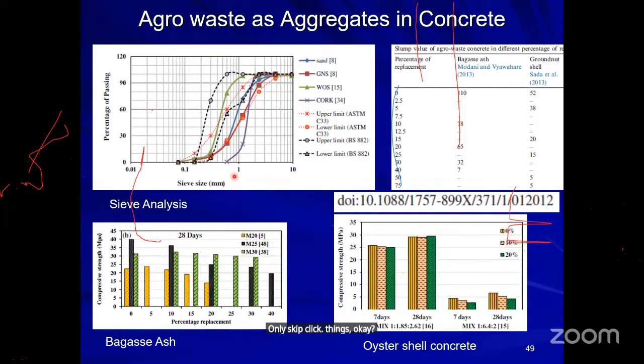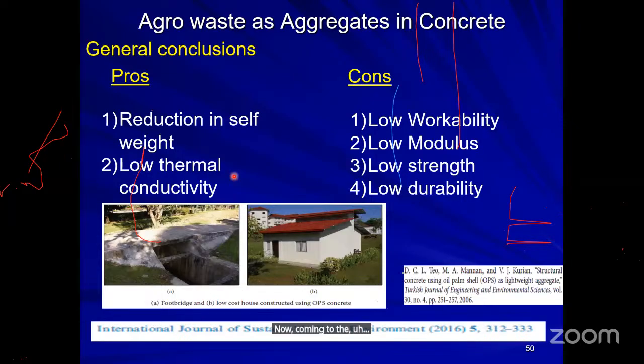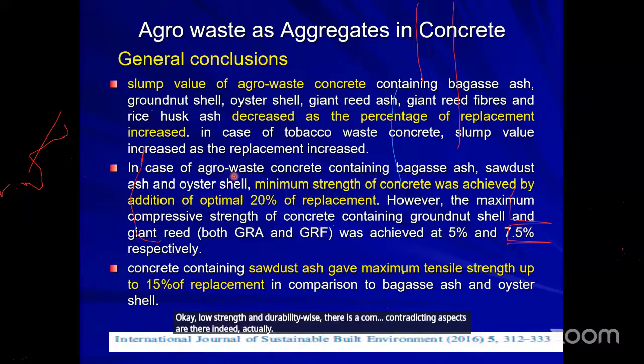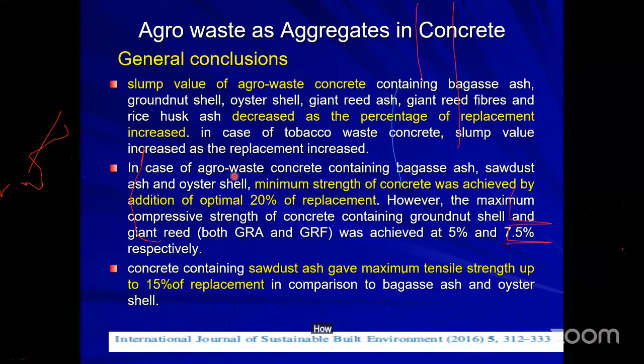Now coming to the agro waste pros and cons. The pros are reduction in self weight and low thermal conductivity, which is one of the advantageous parameters. But when it comes to the disadvantages, it may result in low workability and low modulus. Low modulus means there is a possibility of slightly higher deformations. Also low strength, and durability wise, there are contradicting aspects. Of course, all these things I've taken from the literature. You can also go through the literature on how people have used and concluded on these agri wastes. For example, the slump value of agro waste concrete containing bagasse ash, groundnut shell, oyster shell, giant reed ash, etc., decreased.